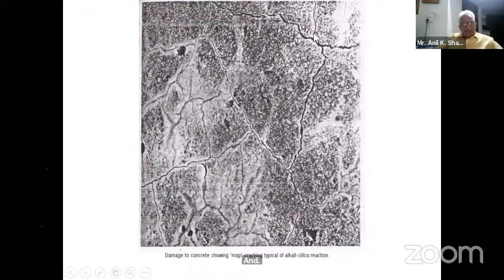These are the cracks which could be on account of excessive sulfate in the concrete, in the cement paste that we have used, or these cracks could be on account of the alkali aggregate reaction also.